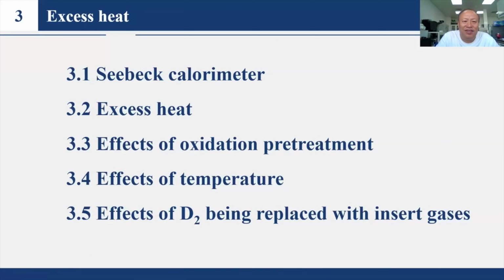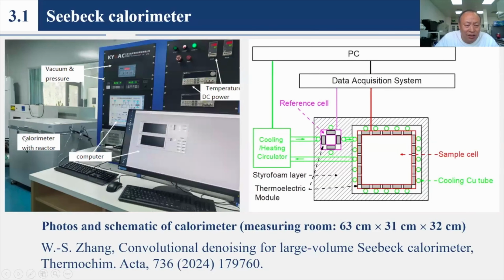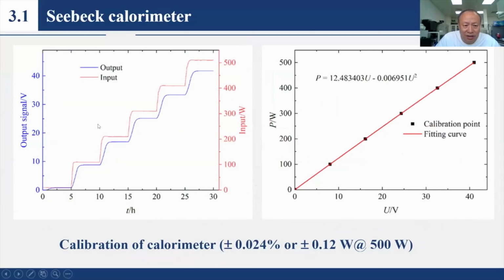Then is the most important result, calorimetry of the samples. On the left corner is the calorimeter, our Seebeck calorimeter. We have 3 Seebeck calorimeters of this type. The measurement chamber of the calorimeter is 63 centimeters by 31 centimeters by 32 centimeters. This is the calibration result. We have calibrated it up to 500 watts, with an uncertainty of only 0.12 watt, or 0.024%.